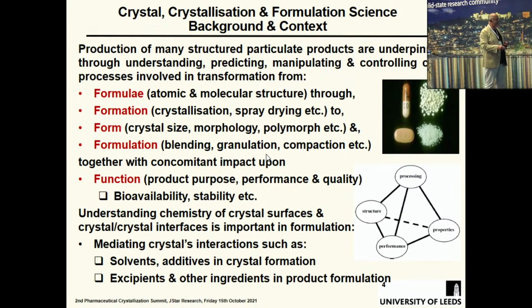Understanding the chemistry of crystal surfaces, and particularly crystal-crystal interfaces, is important in formulation. That is why we need to look at the morphology of materials, because it's the surface chemistry, where the intermolecular interactions are broken, and those broken interactions drive the product properties. And these interfaces are mediated by solvents, additives, crystal formation, and, more importantly in formulation, the excipients and the other ingredients we put into a typical tablet.